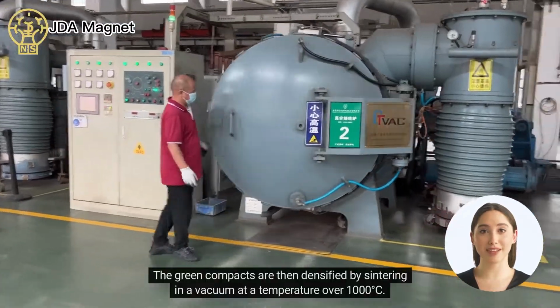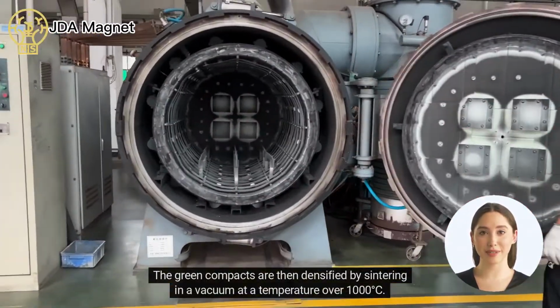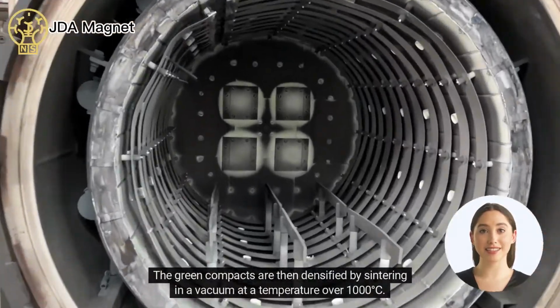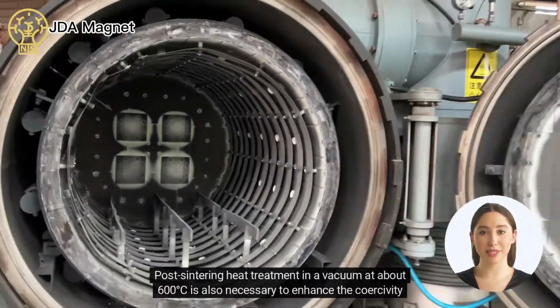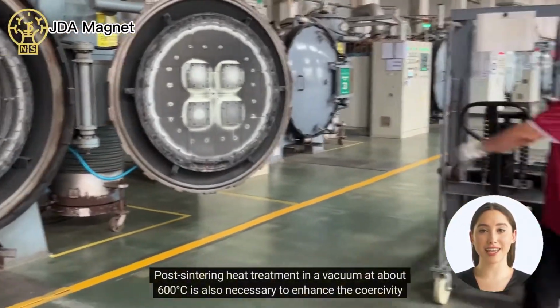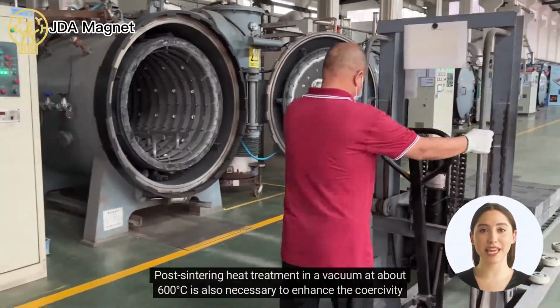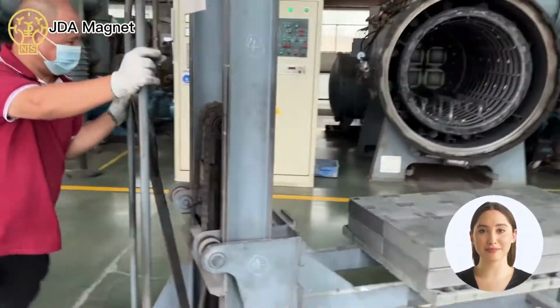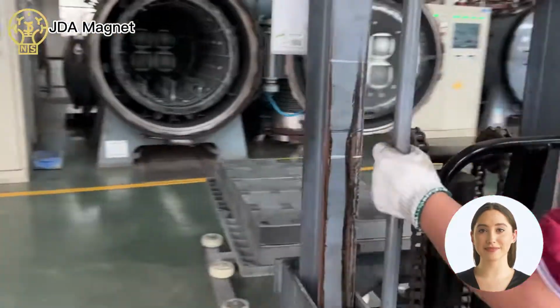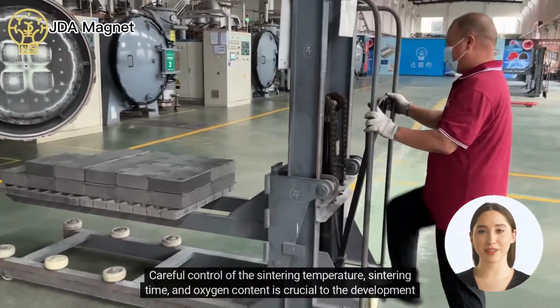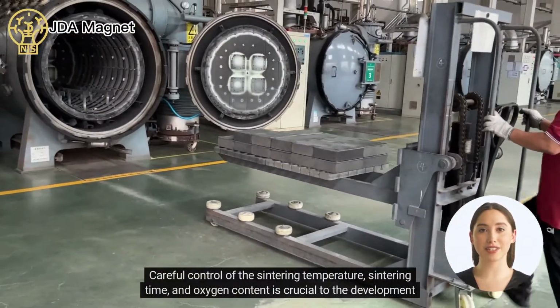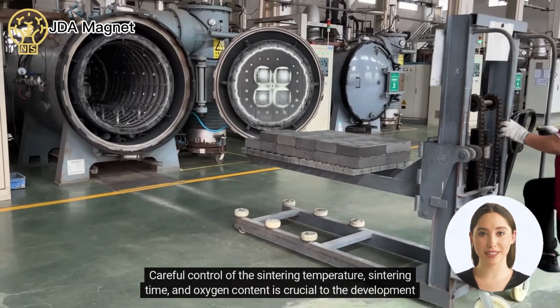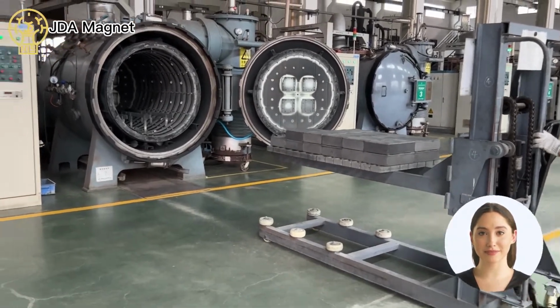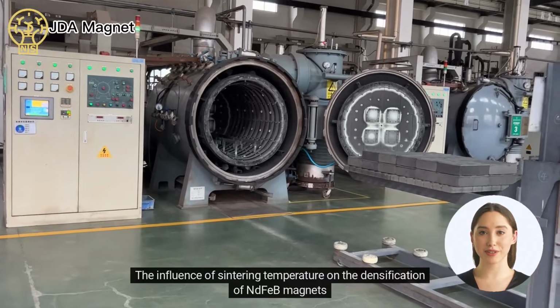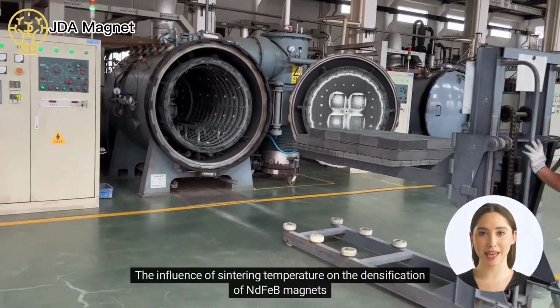The green compacts are then densified by sintering in a vacuum at a temperature over 1000 deg C. Post-sintering heat treatment in a vacuum at about 600 deg C is also necessary to enhance the coercivity of the magnet. Sintering will solidify the magnets. Careful control of the sintering temperature, sintering time, and oxygen content is crucial to the development of the properties of the final magnets. The influence of sintering temperature on the densification of NdFeB magnets.